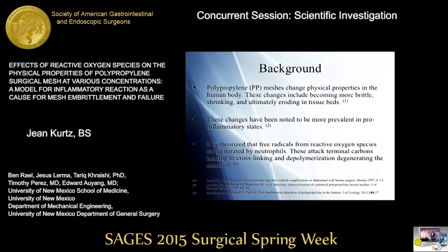Also, the theory behind this is that free radicals from reactive oxygen species released by neutrophils, for example, hydrogen peroxide, are causing these changes. The free radicals can attack the terminal carbon of a polypropylene, which leads to depolymerization, cross-linking of the chain, and ultimately degeneration of the material.